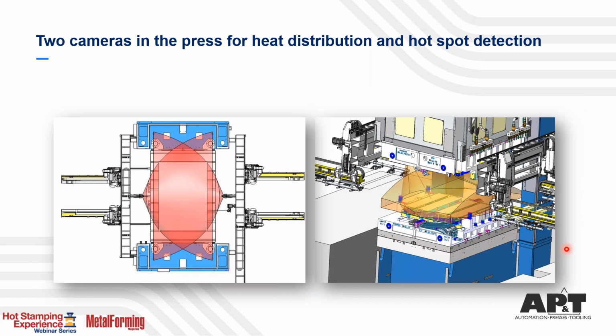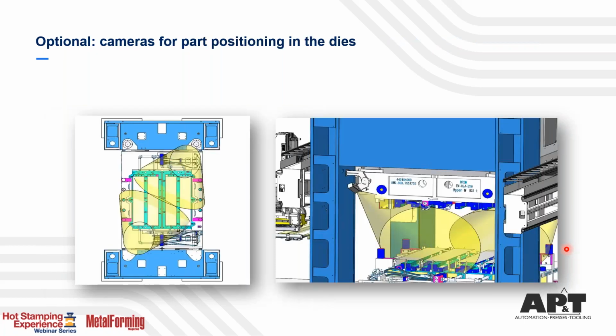We would actually recommend installing two cameras, where we have incoming temperature measurement when coming in with the hot blank, as well as after opening the die, where we have hotspot detection. So we measure heat distribution in the blank, which also gives you an idea about your heat treatment process in the furnace, where you can detect failures if something is wrong with it. And then more importantly, hotspot detection for checking on die wear, for example, an important parameter to watch.